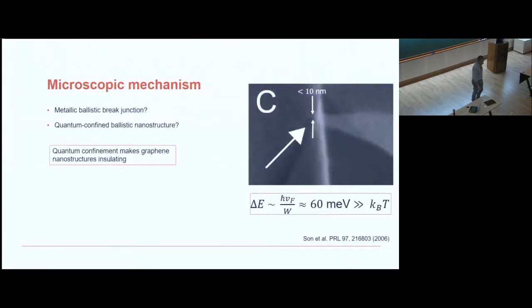It's not a metallic break junction. There are previous cases of this sort. If you take a gold metal, you break it, you get a metallic break junction, but that's not the case here. That's because at this confinement, graphene is supposed to be an insulator. It's not a metal. It's a semiconductor. You open a quantum confinement gap of 60 millielectron volt, which is significantly larger than the temperature. The system should have become an insulator. It is not so. It's actually a metal with a very high conductance of 2e square by h.